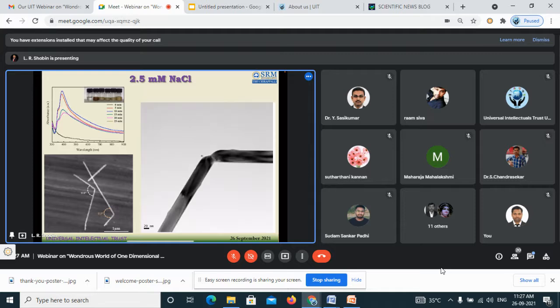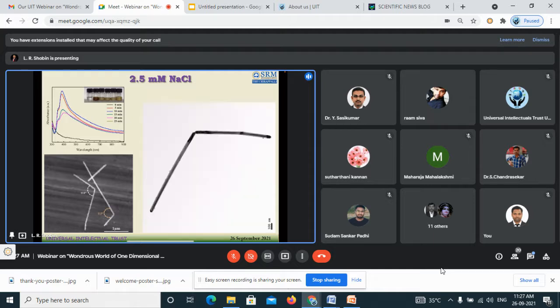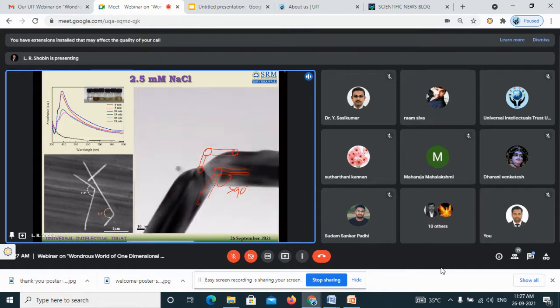These angles are all greater than 90 degrees, so they are all obtuse angles actually. What is happening is, if you consider one particle over here, once you supply a small amount of salt, this particle started to grow at this point. From one particle, the wires started to grow like this. So you will end up with wide-angled, greater than 90 degree wires in this system. So these are all the fusions.